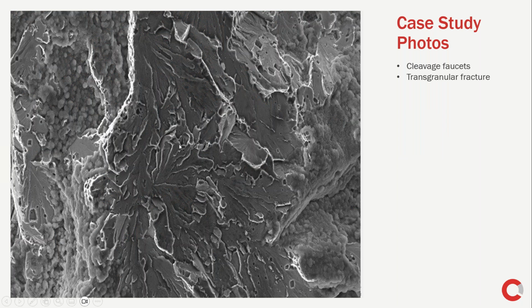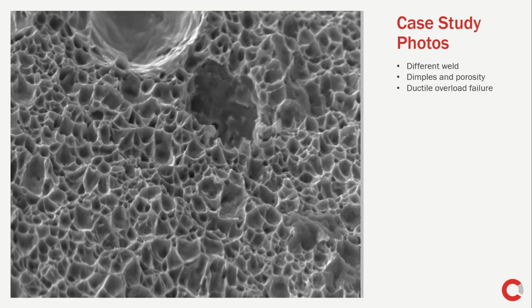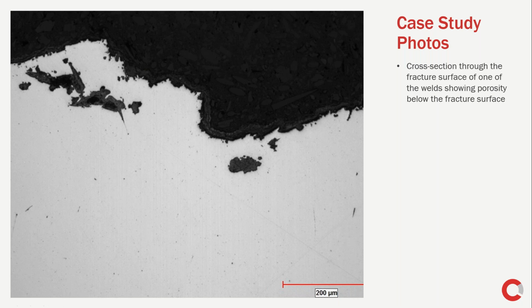Looking at a fracture surface similar to the one on the previous slide, we saw brittle failure, which indicated a problem with the weld. Some of the welds failed as intended in a ductile manner, and this is a typical appearance of a ductile failure, although there are some voids present as well. Further metallurgical examination in the cross-section revealed porosity below the fracture surface. This is the fracture surface on top, and those dark features here represent porosity, which are, as I mentioned, undesirable.